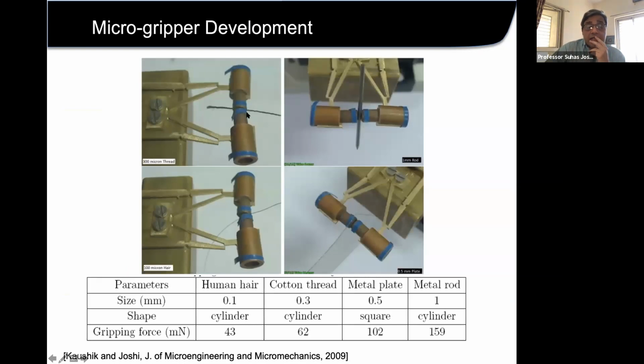The interesting result here is that there are two concentric cylinders, and the inside one has a spring. So when the jaws come inside, they only apply a force which is enough for holding, suppose, a hair or a nail or a simple glass plate. Only that much force is applied. It doesn't apply more force, because you have a spring in between the two concentric cylinders, and that spring is pre-calibrated. These blue dots are markers that can be seen by the top camera. And now you can see the displacement of the springs and calculate the force it is applying to hold a hair, a thread, a nail, or a glass plate.